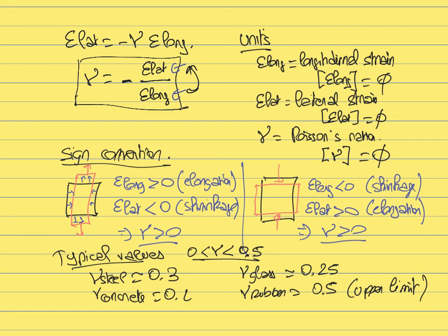If you have a material like rubber with a very high Poisson's ratio, then when you expand it, it shrinks laterally a lot. So for a given longitudinal deformation, the resulting lateral deformation will be very large. And this is because for rubber, the Poisson's ratio is very large. So try to keep in mind that a large Poisson's ratio means large lateral deformation. So the Poisson's ratio should be proportional to the lateral deformation, not inversely proportional to the lateral deformation.